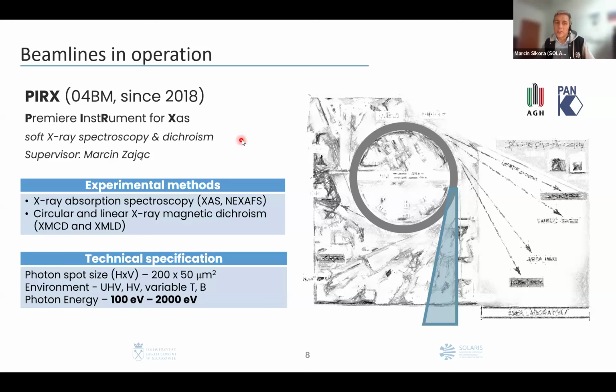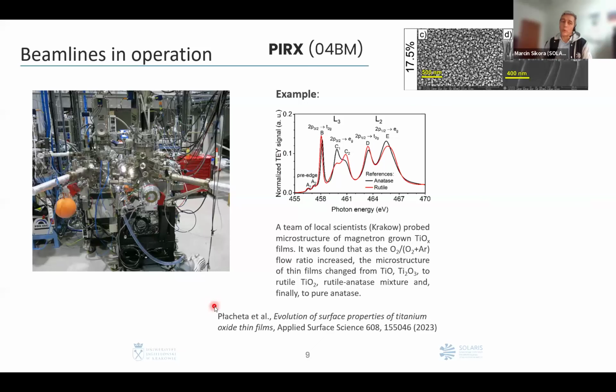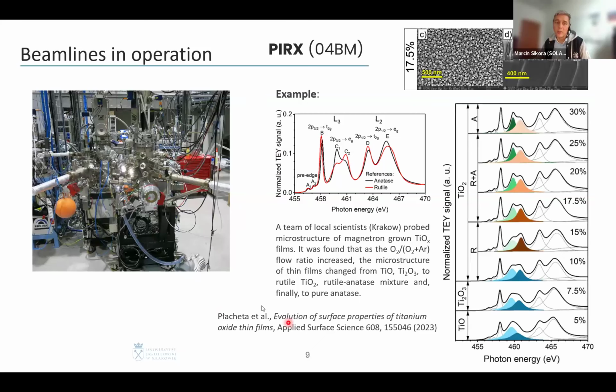So this beamline PIRX is devoted to soft X-ray spectroscopy, basically X-ray absorption spectroscopy, near-edge X-ray absorption fine structure, and also to the circular and linear magnetic dichroism. So the energy range roughly is from 100 electron volts to 2000 electron volts. And just to give you a flavor of one of the possible experiments, that's an example of titanium dioxide films of the order of 200-300 nanometers thick. The films were prepared for water splitting, and the question was how to optimize their internal structure.